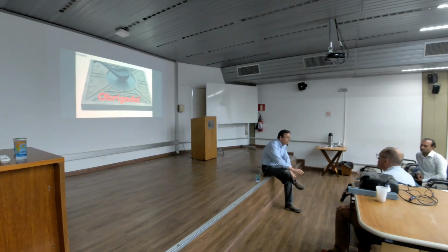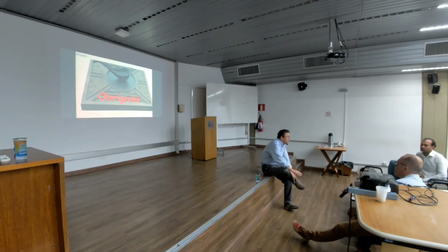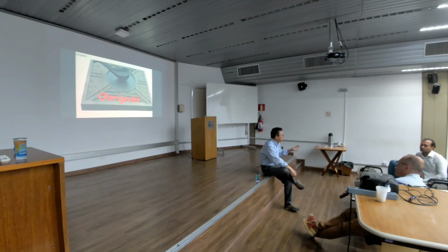So, in view of the economy, we need permanent magnets not based on rare earths, because now there is a gap in the permanent magnets market. You can either choose ferrite, which is very cheap and very stable, but the energy density is very low, with an energy product of about 5, 6 or 7. Or rare earths, neodymium-iron-boron, which are expensive but high performance. There's not much in between.